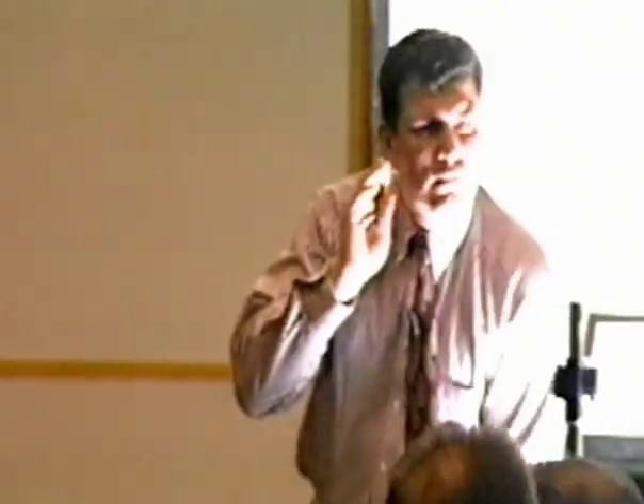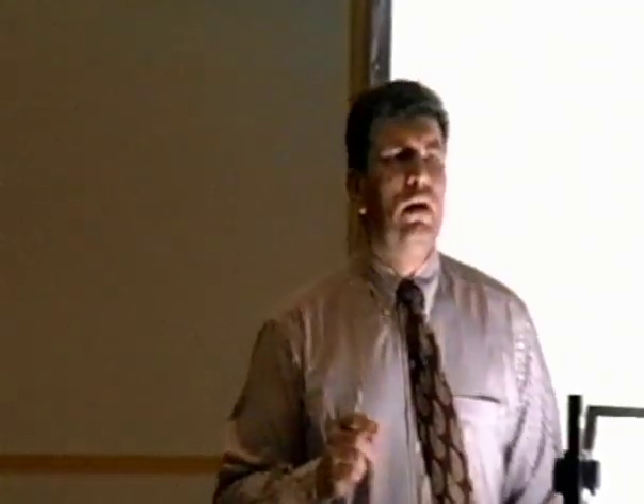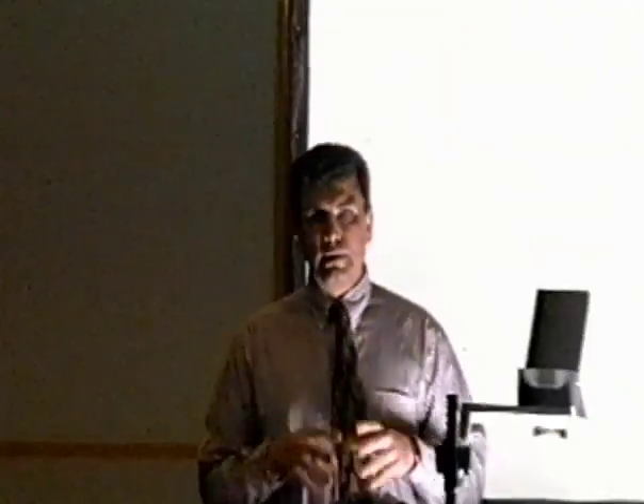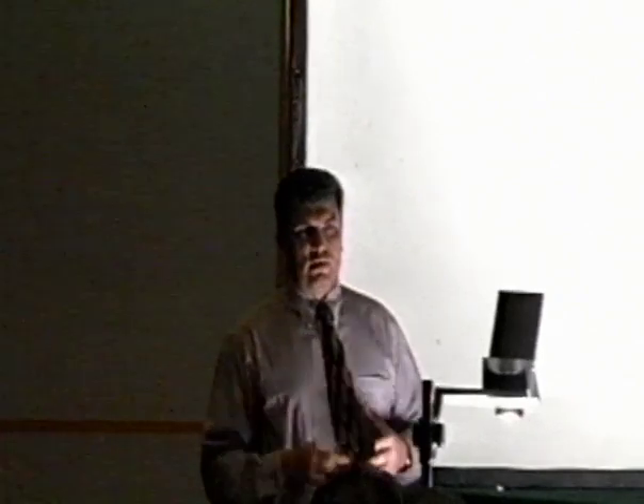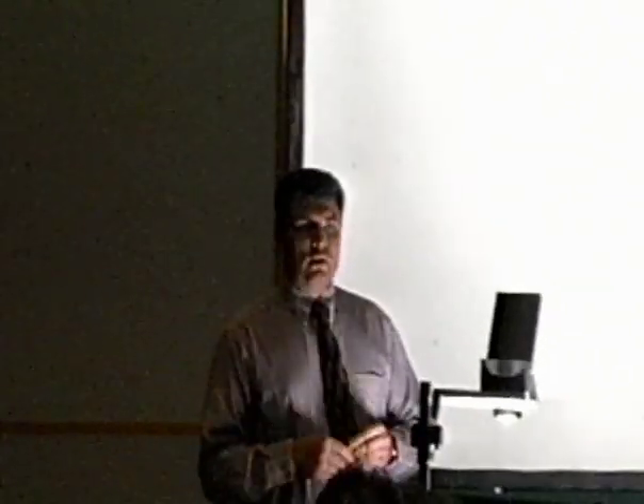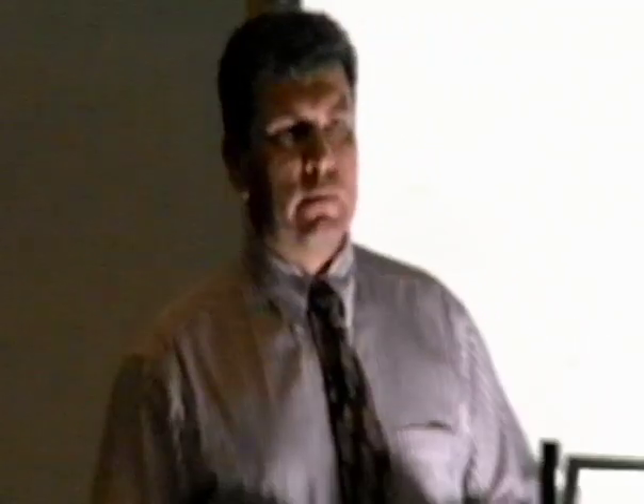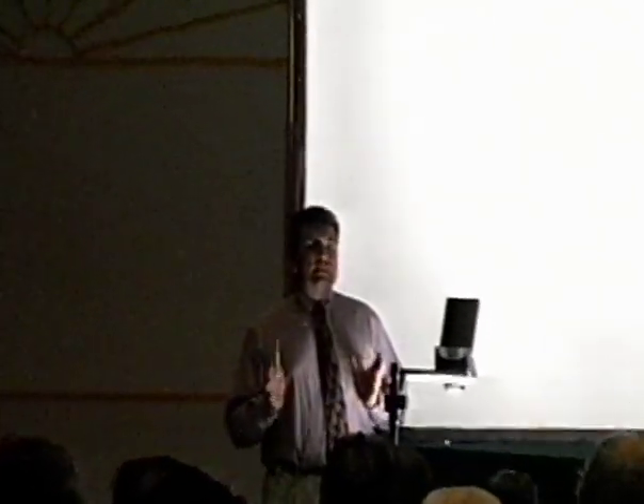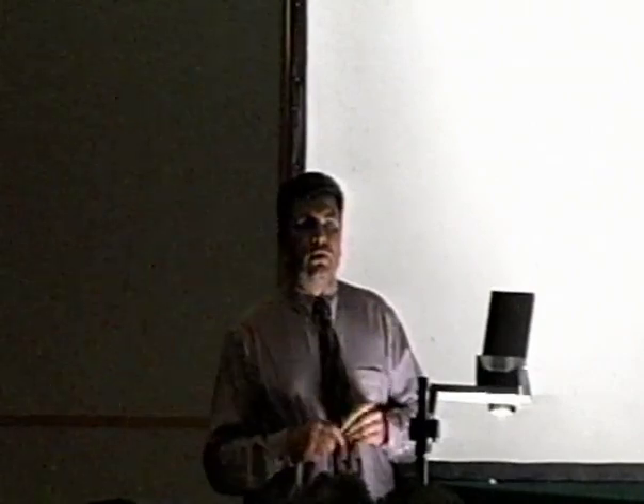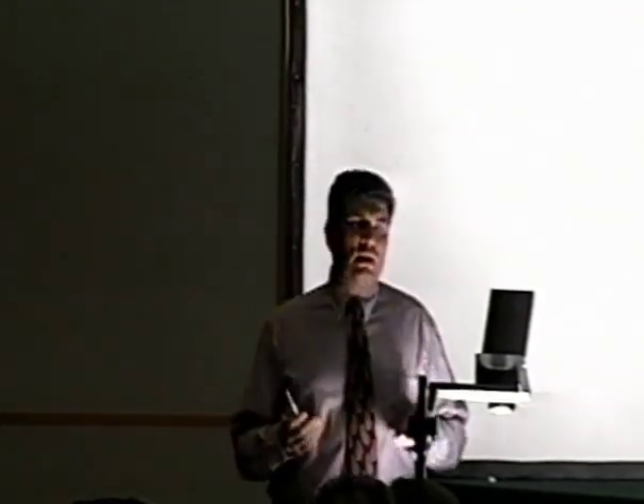Could you say something about the calorimetry, total energy? Well, this is microcalorimetry. What makes us very confident about this result is that this is not a single scientist's work. It was teamwork. About seven scientists were involved, and 2 of them are top Russian scientists in microcalorimetry of molten salt systems. The power applied to the cell was about 0.97 watts. This is a really small cell, heated to about 370 centigrade, but this is a really small energy level. And the heat which we observed was about 0.08 watts, so approximately 10%.